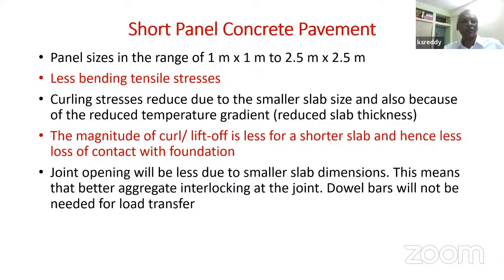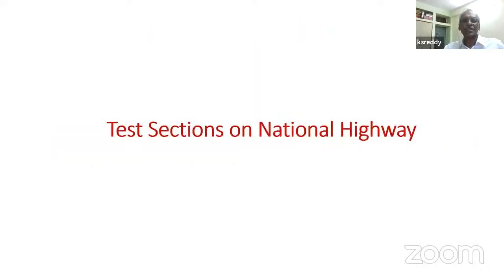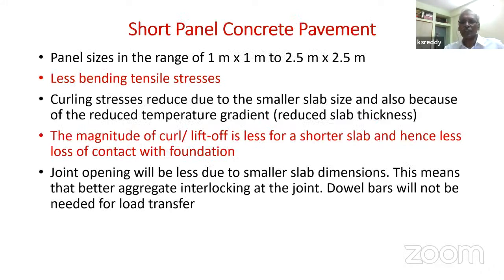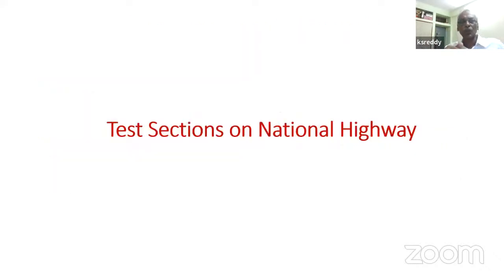As already mentioned, there is smaller magnitude of bending stresses and smaller curling stresses. The main issue here is you have more joints to be constructed and you have to maintain them. But since the joint width is smaller, the roughness or comfort level is expected to be better compared to more conventional concrete pavement, where the joints are going to open up much wider.